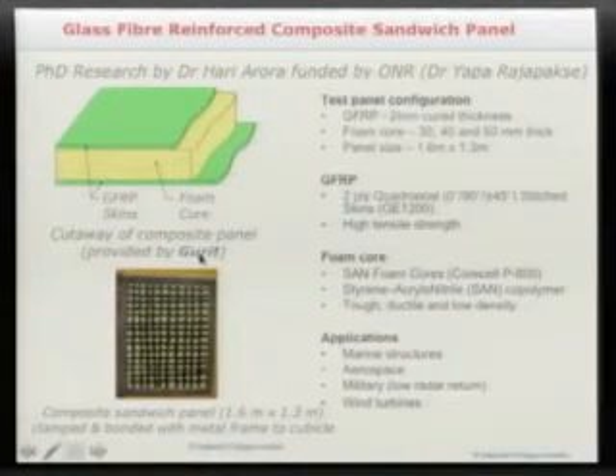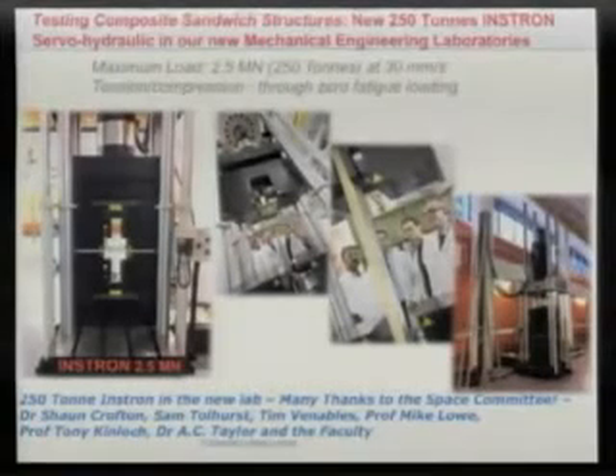So what we did is we went to Gurit on the Isle of Wight and asked them if they could make for us some composite sandwich panels which would be representative of marine structures, so that we wanted large-scale structures. And they fabricated for us panels which were typically about 1.6 metres by 1.3. They've got different foam core thicknesses, and we've got skins which are about 2 millimetres. And we took those to the north of England and did some blast tests on those. We also evaluated them in our lab. And this shows one of those big samples being evaluated in the 250-ton Instron.